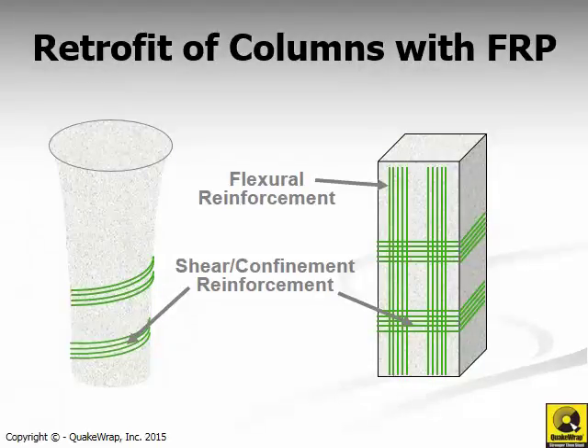And if you recall from our first portion that we talked about introduction to FRP, the strength of FRP is proportional or directed to the orientation of the fiber. So in this case, for example, as shown in the column on the left, if we are interested in only increasing the shear behavior of the column, we can wrap the fabrics in the horizontal or in the hoop direction. If we are interested in providing both flexural strength and shear confinement, that would be the one shown on the right, where we put some of the fibers vertically and some in the horizontal direction.